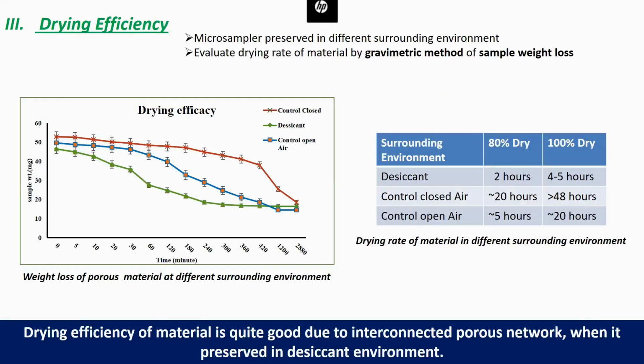Further, we tried to dry our device in different conditions, like a controlled closed container with the help of a desiccator, and a control open area. We see that in the case of the desiccant, our device would dry 100% within 4 to 5 hours, whereas the control open air took longer to dry. This is very essential if the sample needs to be collected in hot and humid conditions where the sample may get degraded. It should be dried quickly to be easily transported.